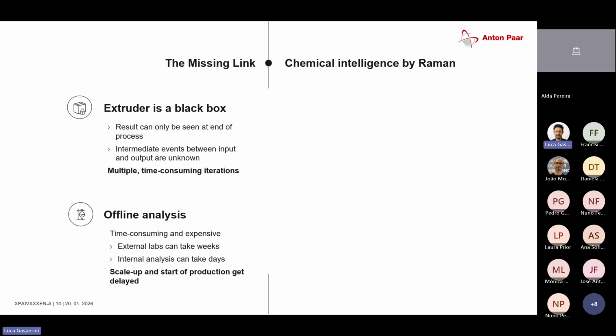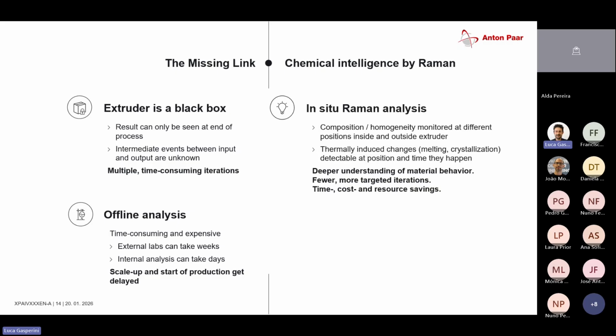If any of the properties, let's say thermally, does not behave as intended, I have to go back to the extruder, change something in the recipe, and repeat the whole process. So this takes a lot of time. And also when I scale up, or scale up a part of the process, the sample could behave differently. So this is why in situ Raman analysis is really of use. As I said, you can measure the composition or the homogeneity of your melt, and you can also see how it behaves thermally.